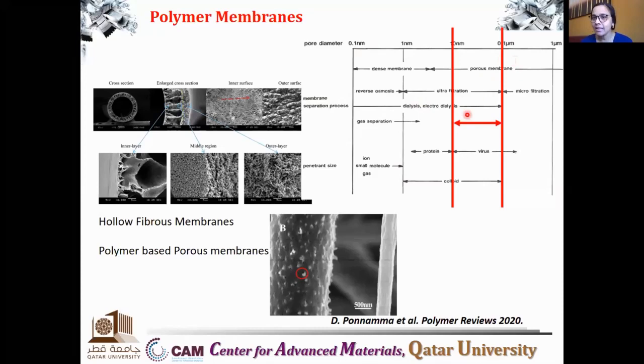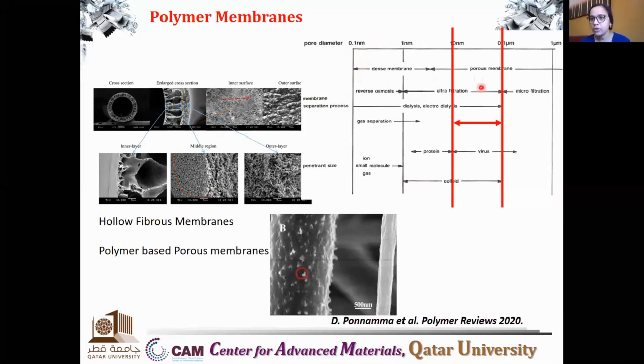This is the pore size. And while considering the oil water materials, here comes the reverse osmosis membranes, which we use for desalination purposes. There we need much less pore diameters. But oil molecules are a little bit bigger than the salt ions, right? So we can concentrate on creating polymeric membranes with pore size ranging from 10 nanometer to 0.1 micrometer. So this is the ideal range we need for the polymeric membranes. It is a very important number.